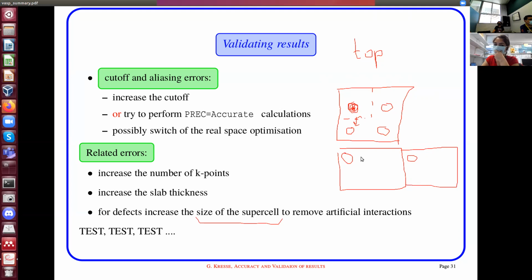So in this case, for instance, you have maybe a size here that is like 8 angstrom, and that is good enough, because at 8 angstrom, this and this will not feel that much repulsion, okay? So there will not be repulsion. It means that whatever is happening here will not affect this one, and that is what you want to achieve, because unless you are considering high coverage simulations, normally you are assuming that there is no interaction between one image and its periodic image.